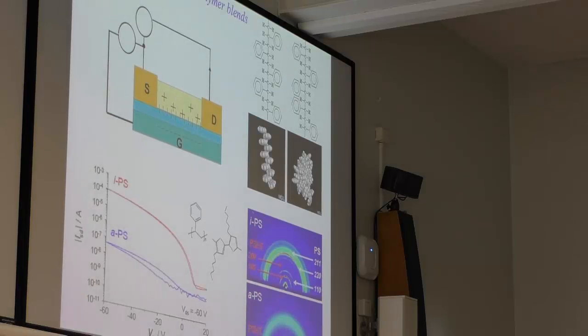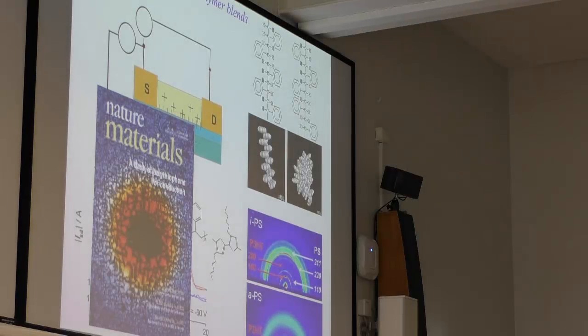And also when we correlate this to the scattering patterns, one can see that clearly in the atactic polystyrene there are no sharp diffraction patterns consistent with this material being roughly amorphous. But what is more interesting is that the electronically active material, the polyhexyl thiophene, the crystallization of the polystyrene promotes the crystallization of the polyhexyl thiophene. So if you want to read more about this, you should look into Nature Materials from 2006.